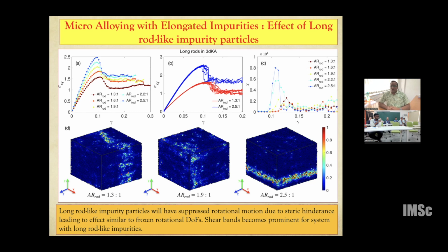It looks like promoting shear bands in a particular region. But also note that in these snapshots, rods are actually distributed everywhere. It's not that they're all aligned in the shear band. But somehow their presence leads to much sharper shear band formation. Are these shear bands devoid of the elongated rods? No, they are uniformly everywhere. It's not that their concentration increases in the shear band. They are still uniformly distributed in the sample, but somehow shear bands are much thinner.